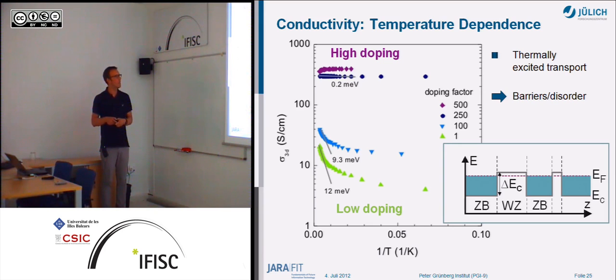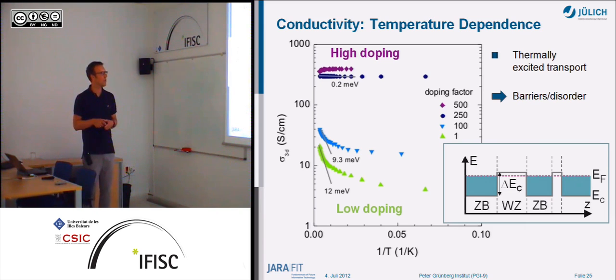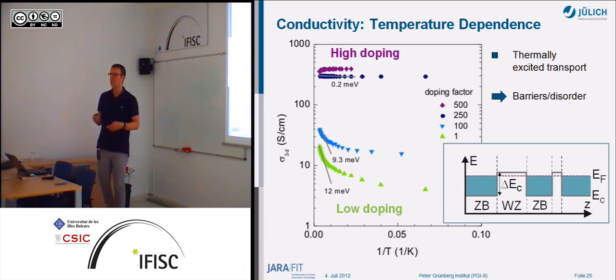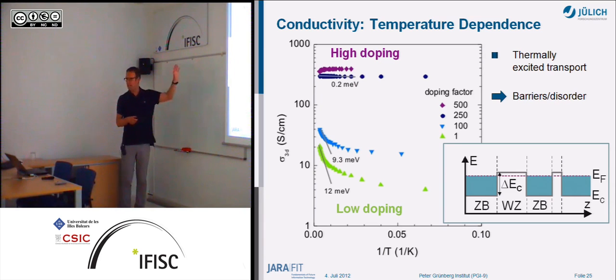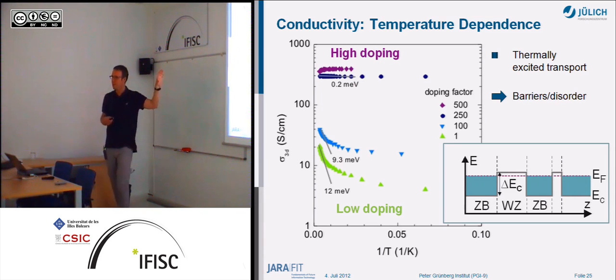If you increase the doping, you increase the Fermi level, and then it's getting easier for the electrons to get transported through the nanowires because the barrier they have to overcome here is getting smaller. Yeah? And that's what you see here. If you have a low doping, you have a larger thermal excitation here. Yeah? And if you increase the doping, this high doping level, it's almost metallic because then you have so many electrons that the Fermi level is presumably above all this, and then you have a better transport. So this is something you have to be very careful about if you look at these nanowires.